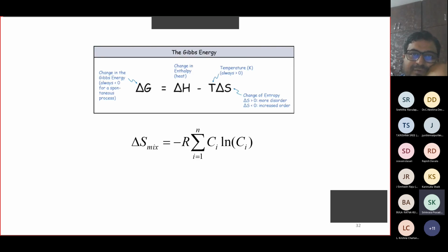Normally, you see this Gibbs free energy equation, delta G equal to delta H minus T delta S. For a given material to become stable, the delta G should be as negative as possible. And for that, there are different strategies, whether you make delta H negative or make delta S positive. The conventional way of developing materials is making delta H negative, and that has reached its limit. And now the strategy is to make delta S more positive so that this whole term becomes more negative, contributing to the more negativity of delta G. And delta S mix follows Boltzmann's equation given here. That shows that if you have more number of elements with different compositions, then your delta S increases. Delta S is the entropy term.